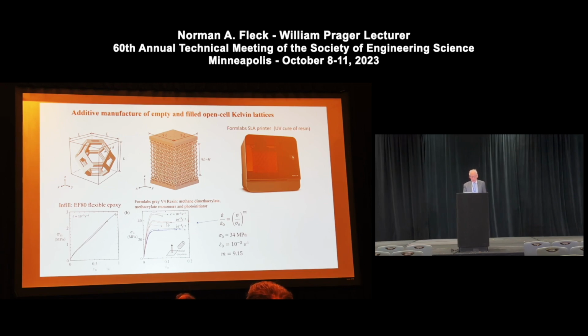Here is the Formlabs response of their grey resin. That's their technical name for it, grey resin V4. If you test the resin alone, the stress-strain response shows significant strain rate sensitivity. In fact, you can think of it as a power law creeping solid with a creep exponent of 9. But reasonable strength here, you see you've got a peak strength in the order of 30-40 megapascals.